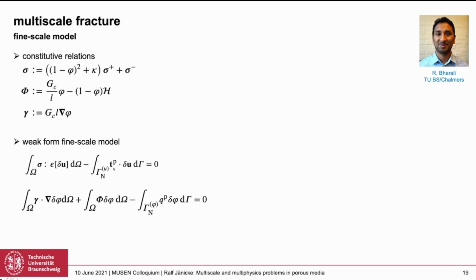All right, without going into detail, there are many different ways of writing down the constitutive relations and the equations here. Basically we have a degradation function, which is measuring the damage state, which is this phi here, which under tension is reducing the stiffness of the sample. We treat this damage variable in a gradient sense. That means we have here a flux of this damage, and also a storage term here.